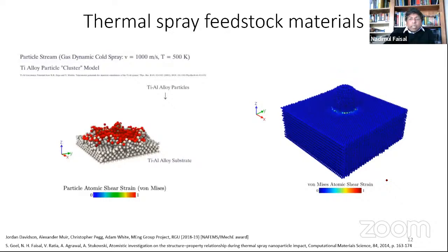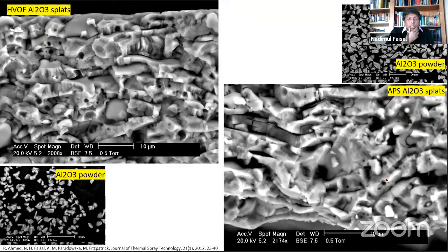Here on the right side, the particle size was large enough. You can see how the strain forms and where it forms. These are important things to look into if you are thinking about developing coatings of very small size. And if you can work it out for one layer, you can have multiple large particles sprayed, and you can get the strain particle by particle or layer by layer. So these are some of the recent work. We know there are about 10 to 15 publications in total in this area where molecular dynamics has been investigated for thermal spray applications. So there's a lot of scope in this area.